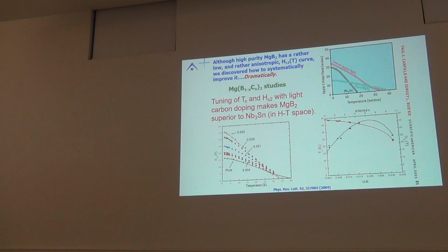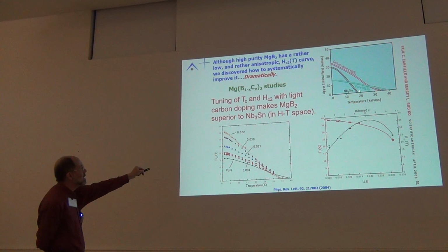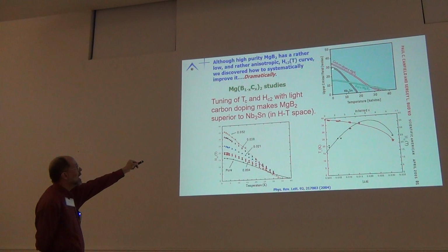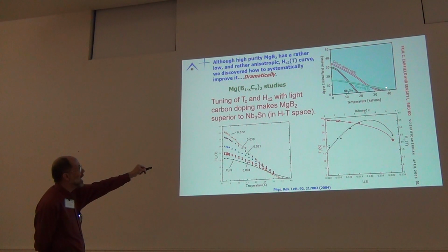Now, we wanted a specific compound, MgB2. We wanted to study the superconducting ground state, okay? We wanted to see if we could improve this, all right? And the reason I want to improve it is, here's niobium-3tin. Niobium-3tin is a well-known superconductor from the 60s, the late 50s. Okay? It has a TC of 17, and David Larbalestier and co-workers optimized HC2 to be around 30 Tesla at low temperatures. Okay? Pure magnesium diboride has a higher TC, but the HC2 was low.